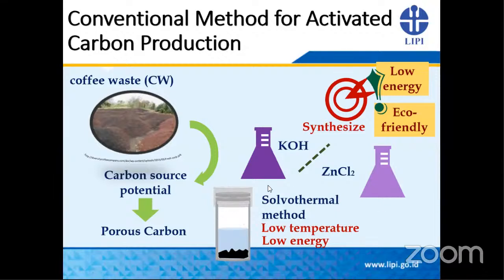So here, we try to use this solvothermal method with a typical, very simple autoclave, to activate the carbonized sample and get a more porous structure in the carbon sample. We hope this kind of activation will lead to lower energy utilization and be more eco-friendly, because the chemical waste here can be used again and again, not only for one-time utilization.